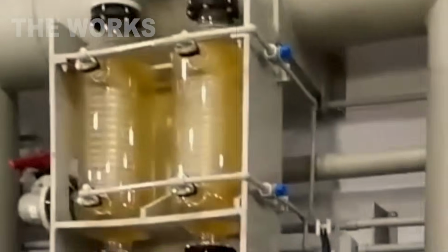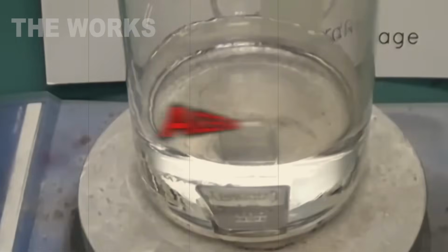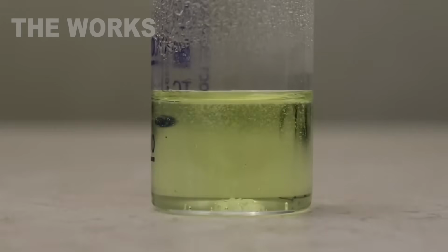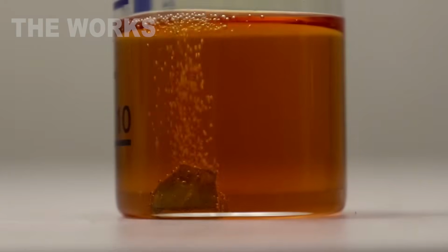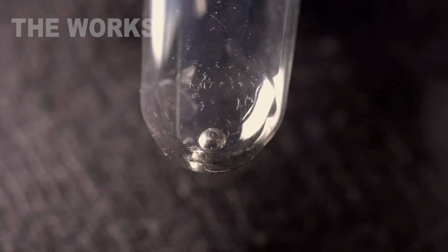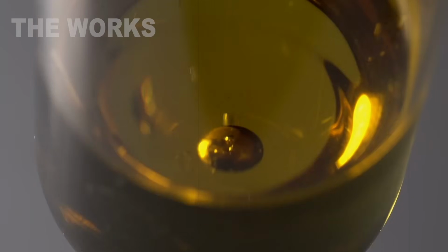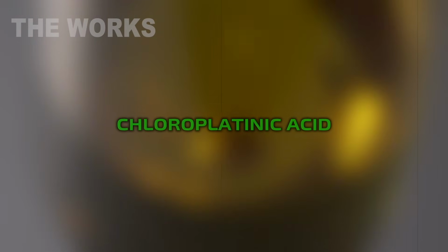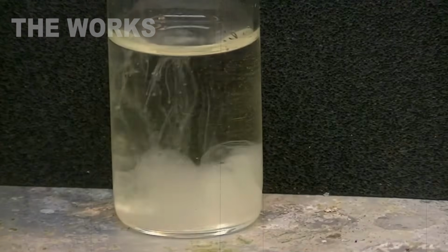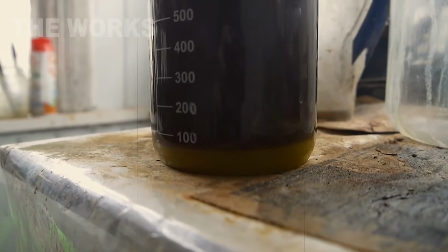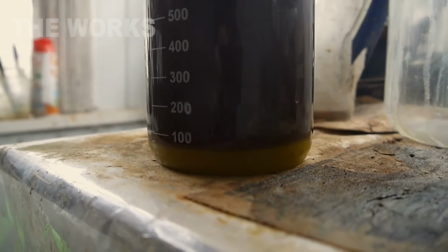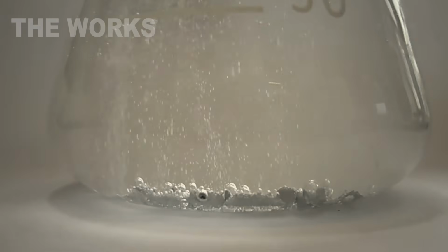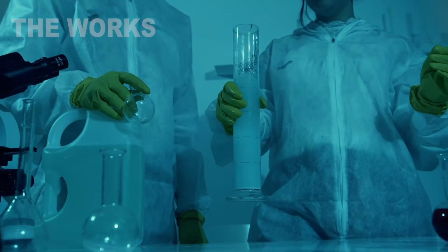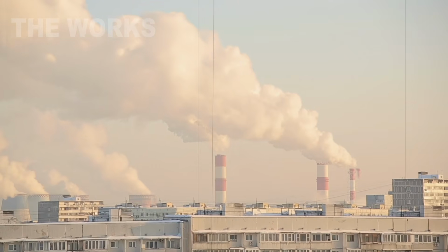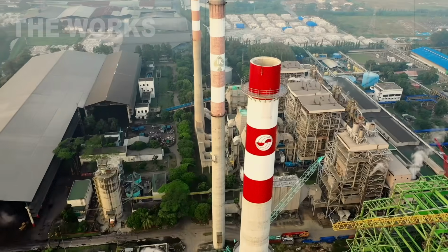Typically, this involves aqua regia, a mix of nitric and hydrochloric acids in a 1:3 ratio. Aqua regia is one of the few acids that can dissolve platinum. When the concentrate is treated with aqua regia, the acid produces chlorine, which bonds with the platinum, forming chloroplatinic acid. The final step uses ammonium chloride to convert the chloroplatinic acid into ammonium hexachloroplatinate, which can be calcined to yield pure metallic platinum. Platinum content in the residue after hydrometallurgical processing can reach 5,900 ounces per ton. That's an enrichment of nearly 500 times compared to the original flotation concentrate.